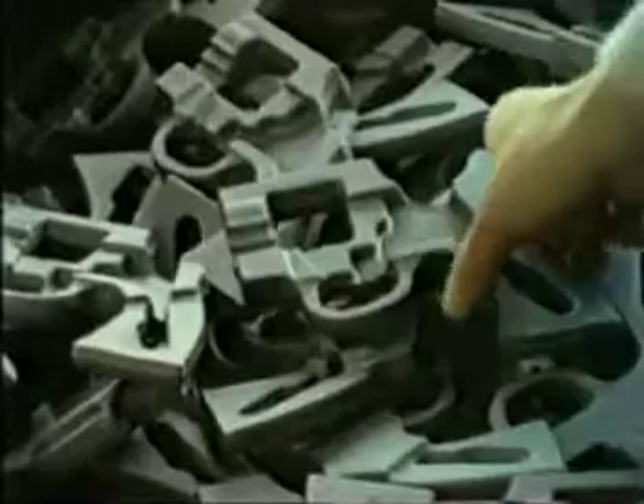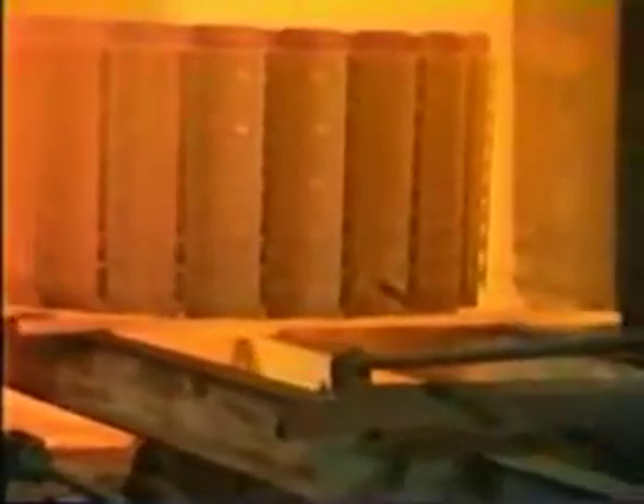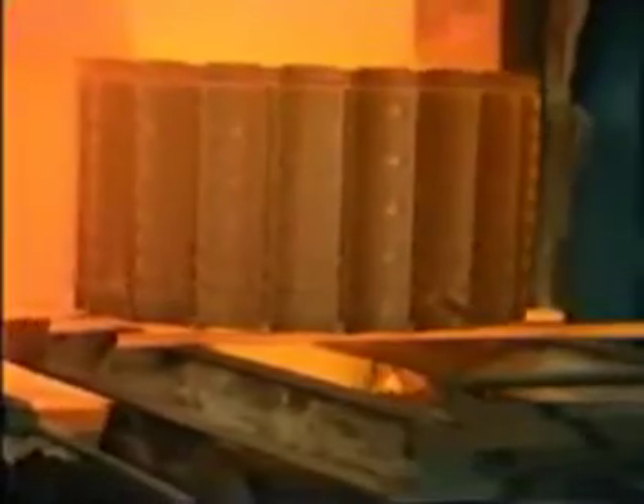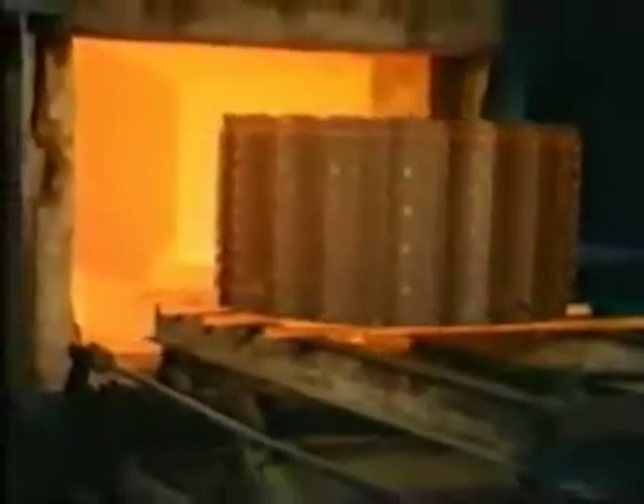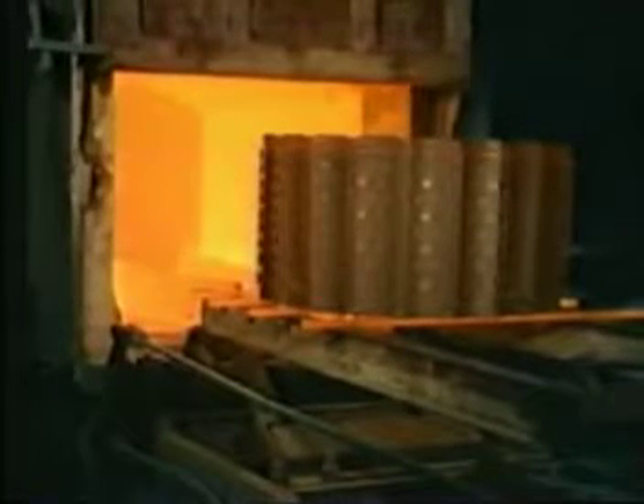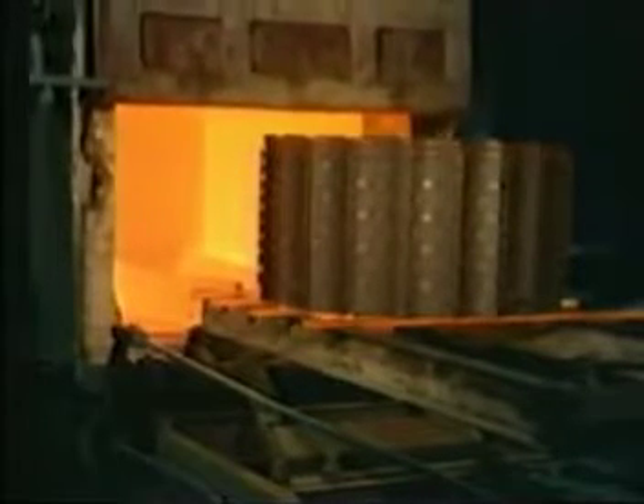Full anneal is a process that requires the metal to be heated to a particular temperature and then slowly cooled, usually in the furnace, back to room temperature. Full annealing is used to soften steel and to relieve internal stresses caused by casting, forging, or a previous heat treatment. Normalize differs from a full anneal only in the rate of cooling. After being heated to a high temperature, work is removed from the furnace and then cooled down to room temperature in still air. The primary purpose of this process is to refine the grain structure before hardening.